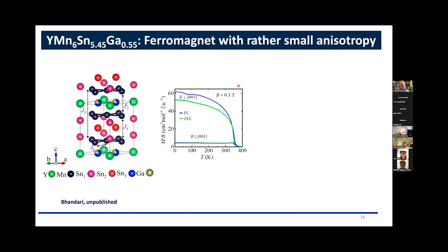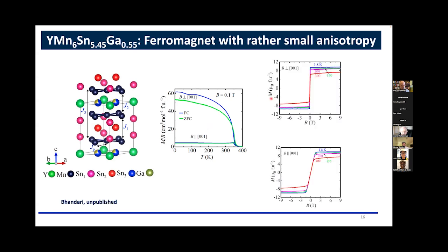But what we realized is that when you dope this yttrium with a little bit of gallium, you don't need much, this is 0.55 of gallium, it makes a nice ferromagnetic system. But now remember, this is a disordered system. It becomes a ferromagnet, and understandably the moments will be in the plane, as in the case of manganese. But the interesting thing is that it doesn't require that much field to get polarized along the C-axis also. It's less than 2 Tesla magnetic field. We can orient the spins along the C-axis and get the ferromagnetic behavior that way.